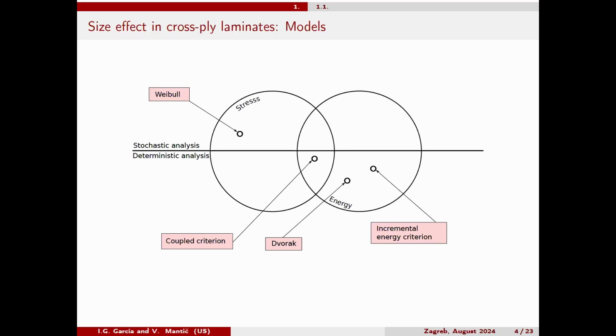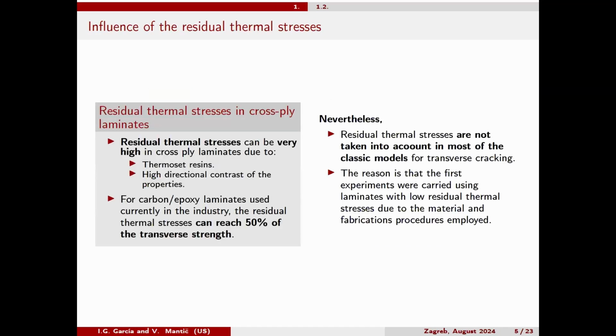But we know that, and if we do some calculation with the laminate theory, we can get that for modern composites, for example, those used now in the aeronautic industry, these residual thermal stresses in some cases can reach 50% of the transverse strength of the lamina. So it's very important, but they are not taken into account in all the previous models. Only the incremental energy criterion takes it into account, in the proposal by Hashin, not the Hashin criterion, another proposal, but they are very important. So the objective of this work is to introduce the effect of these residual thermal stresses on the analysis of this problem, on these different theories.